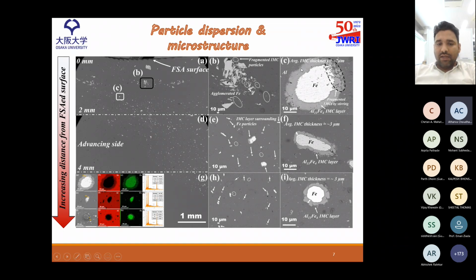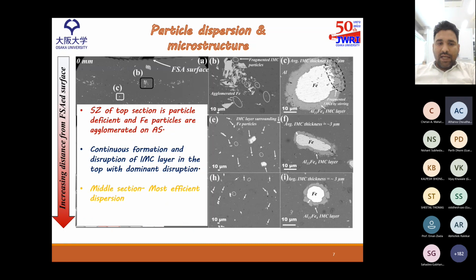We have further classified this IMC layer through energy dispersive spectroscopy, and we have identified that the composition of this IMC layer is equivalent to that of the Al13Fe4 IMC particle. Now, as I discussed earlier, the stir zone of the top section is particle deficient and iron particles are agglomerated on the advancing side only.